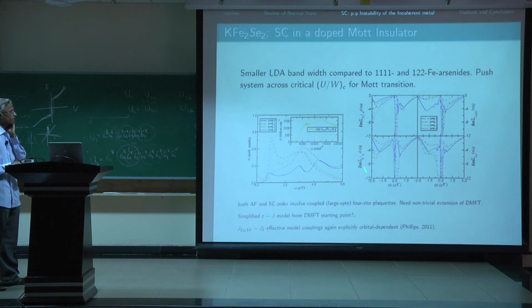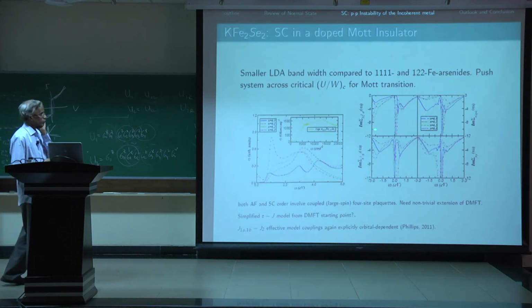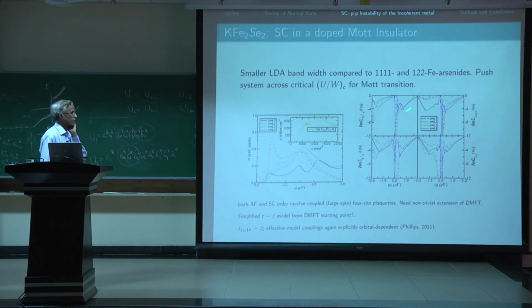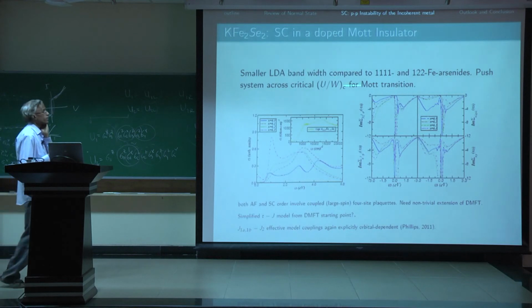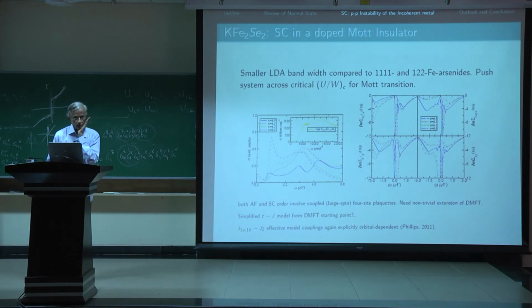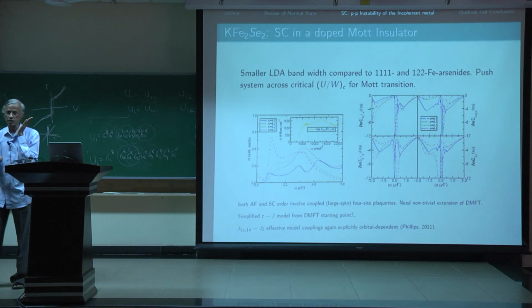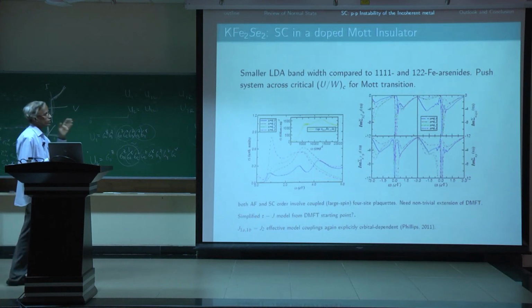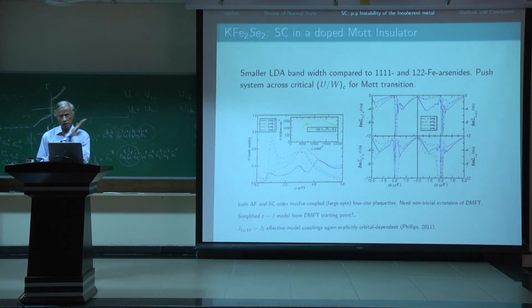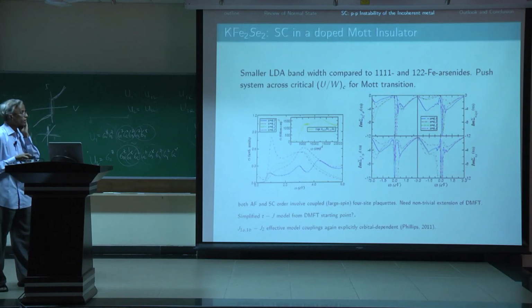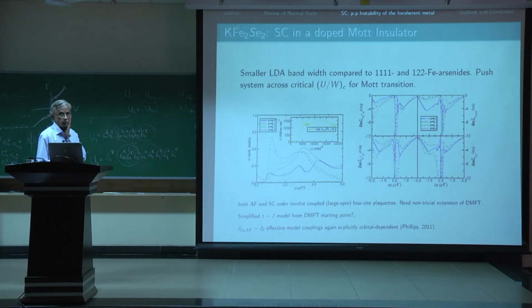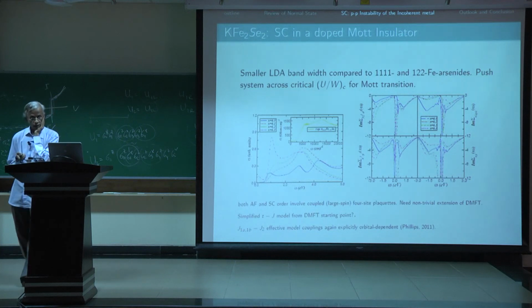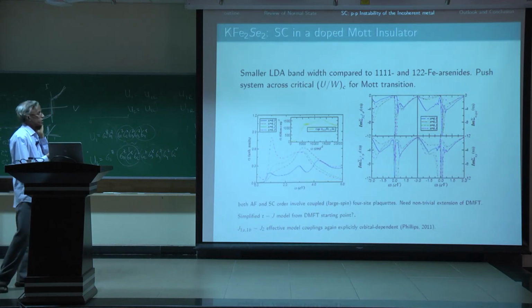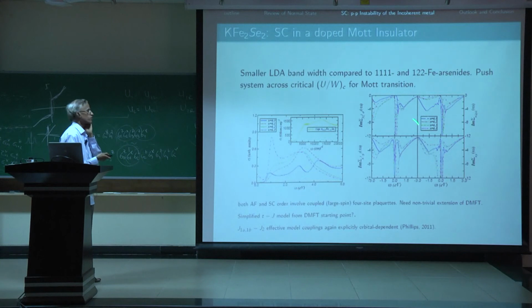Okay, though there the c-axis warping is so small that you cannot induce accidental nodes along kz, and so in that case you would basically say that the pairing symmetry would be extended S plus minus. Okay, so the nature of pairing symmetry, whether you have nodes or not, depends on the fully renormalized electronic structure, which is quirky in a multiband system, depends on the system.